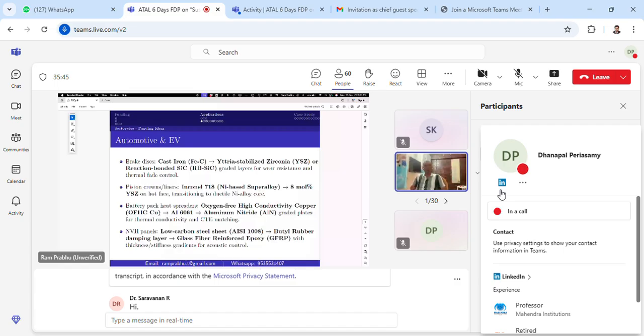So how to avoid? I have a cast iron, and on top of it, I will have yttria stabilized zirconia or reaction bonded silicon carbide. That is a ceramic. So I have alloy, on top of it, I'll have a ceramic. But I will not have alloy and ceramic bonded together or welded together. I will increase the YSZ, that is yttria stabilized zirconia percentage, let's say from 0 on the surface of cast iron to 100. So I will create the linear graded structure, mainly to improve the performance of the brake disc.